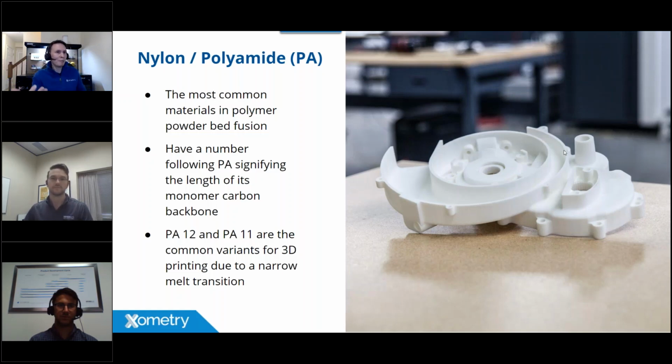So it's the opposite of what I want in injection molding nylon, for example, where I may use a nylon 6 resin that has a fantastic flowability, can get small feature details, and really fill up all the nooks and crannies of a fine detailed design. But that material, when you're using it for sintering, is actually more temperamental because it can get blurry. It can create a little melt pool versus just a nice, clean, discrete melt point when you're doing that. So that's why you see these materials so often.